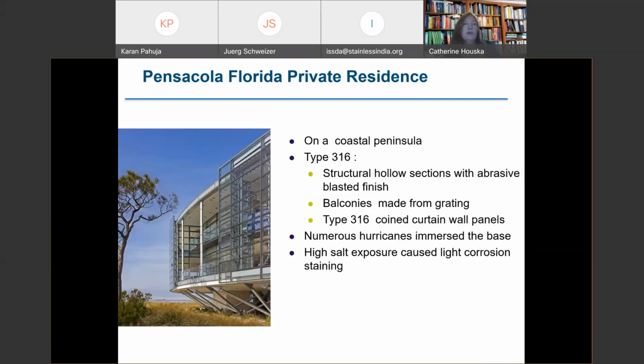This is another very wealthy person's house that I consulted on in Florida. I think his pool house was larger than my house. It is on a peninsula and it is very close to sea level. So whenever there is a hurricane coming through, the base of this house can be immersed in salt. I took a look at it after 3 direct hurricane hits where salt water was splashing up to the higher levels. Everything is type 316, and there was some light staining on it. I was called in to find out how to clean it up. It really wasn't that hard, but at least for the levels that were likely to be immersed, such as the base, a higher alloyed stainless steel might have been a good idea because it would have prevented a lot of cleanup.